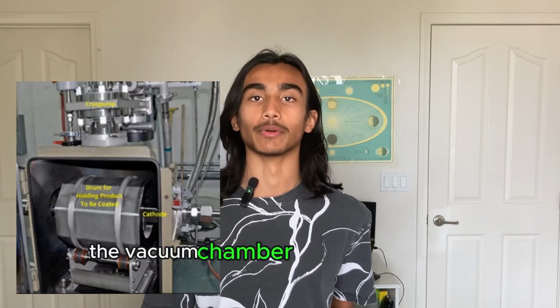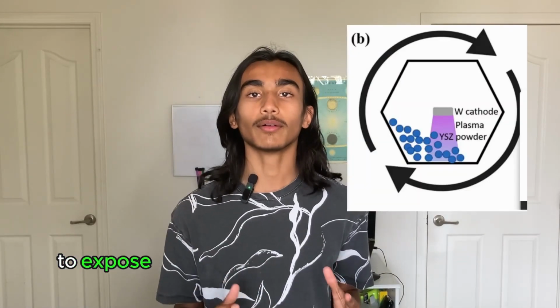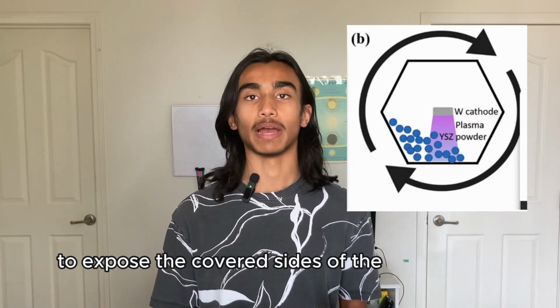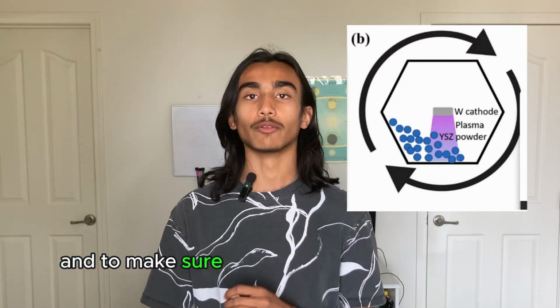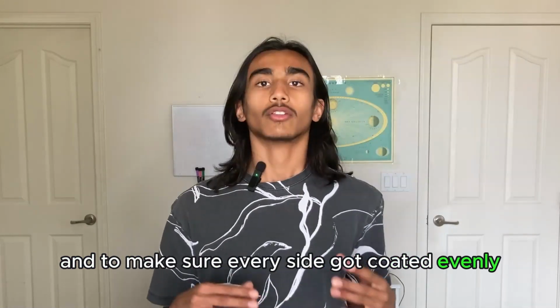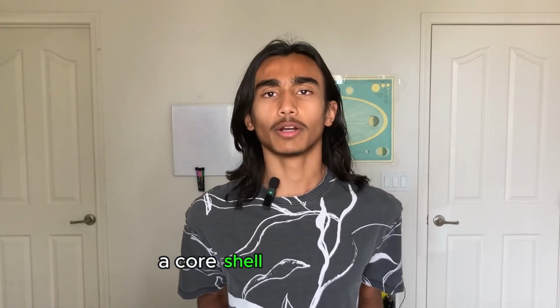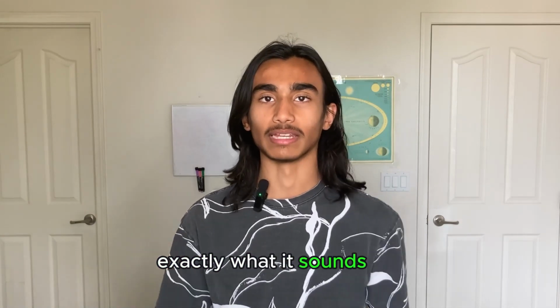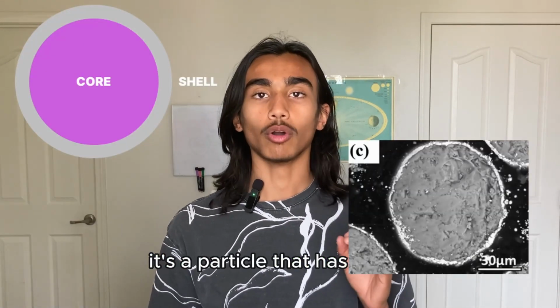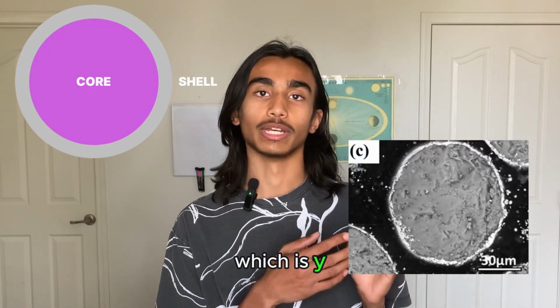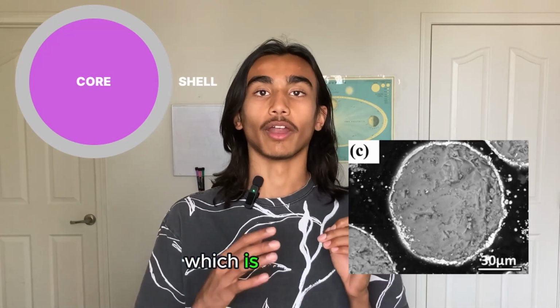This is why the researchers had to rotate the vacuum chamber as the coating was happening, to expose the covered sides of the YSZ powder and to make sure every side got coated evenly. The core-shell particles had a conformal coating under 500 nanometers thick. A core-shell particle is, well, exactly what it sounds like. It's a particle that has a core, which is the yttria-stabilized zirconia, and a shell, which is the tungsten.